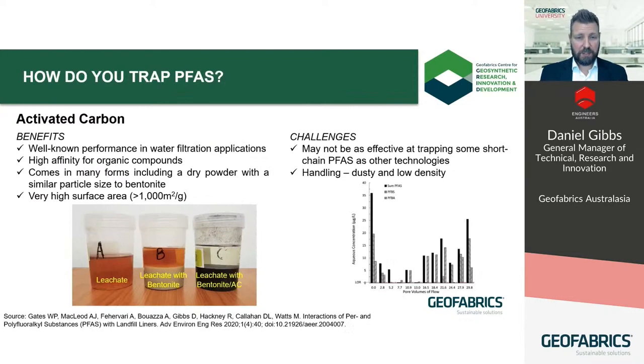So really the question is, how do you trap PFAS? Well, there's a range of products available that can do this, ion exchange resins and other types of polymers. A number of these have been successfully employed by water treatment plants for many years. One of them is activated carbon. Now, activated carbon is one of the most well-known and well-researched products available, with a proven potential to remove organic contaminants such as PFAS from liquids. It has a high affinity for hydrophobic compounds, which is why it works reasonably well to capture a range of PFAS given their hydrophobic tails.